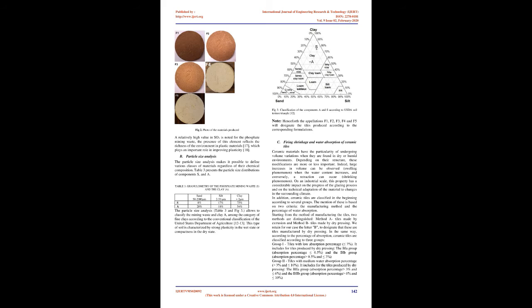Table 2 presents the results concerning the chemical characterization by X-ray fluorescence spectrophotometry of clay A and mining waste S. The chemical analysis, Table 2, of the mining waste shows high CaO, 46.45%, and P2O5, 24.13%, contents, against a low percentage of silica SiO2, 7.41%, and alumina Al2O3, 0.71%. The high CaO content reflects the carbonate nature of the waste, confirmed by a considerable fire loss,